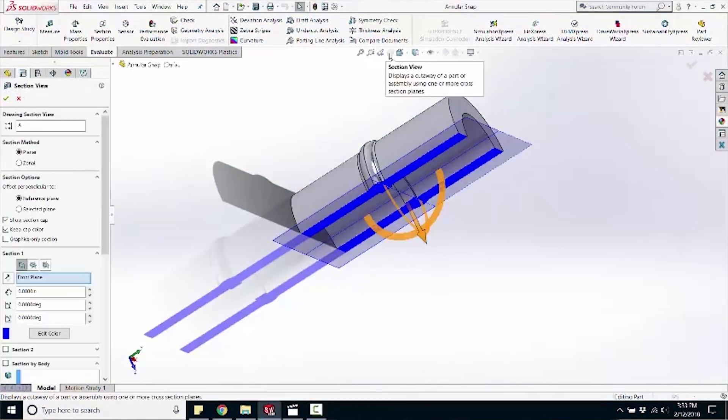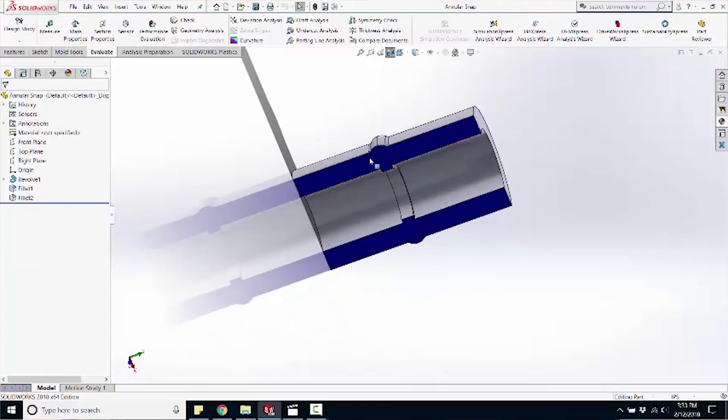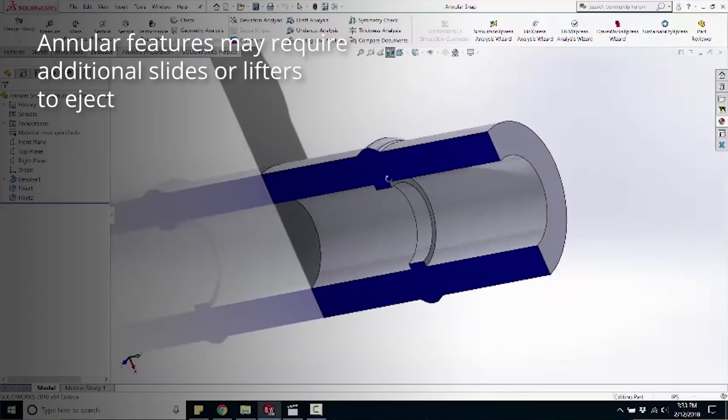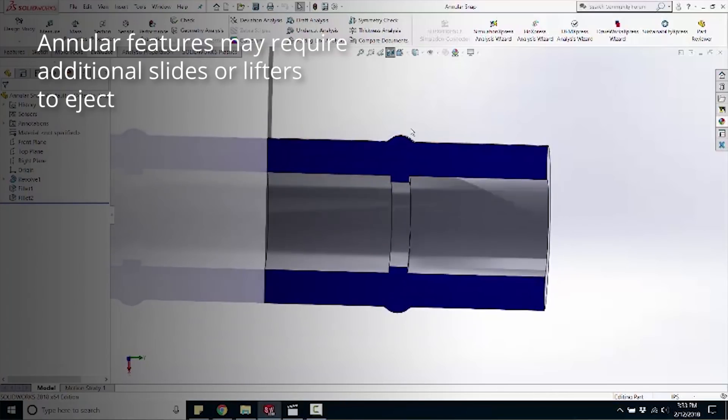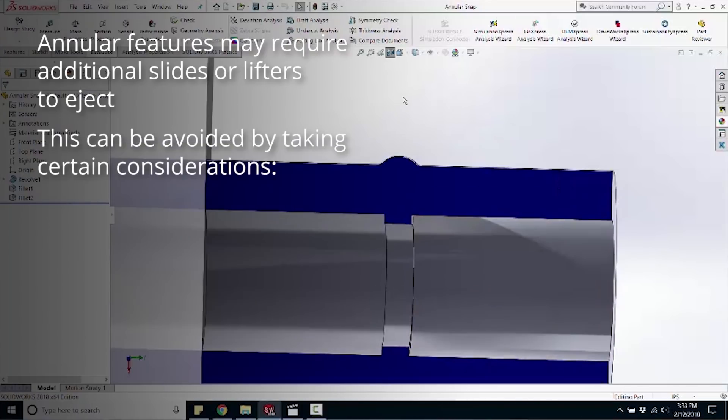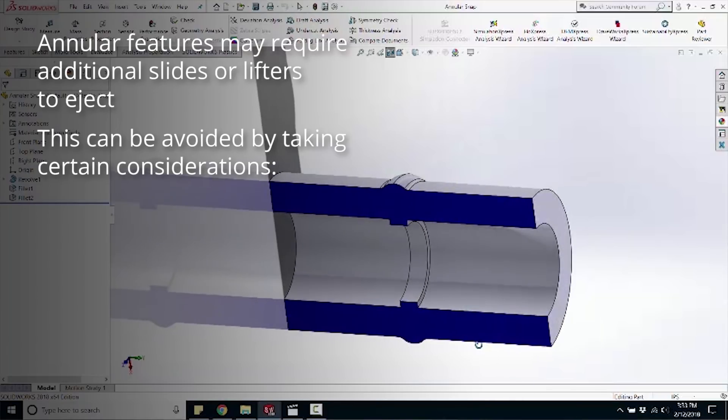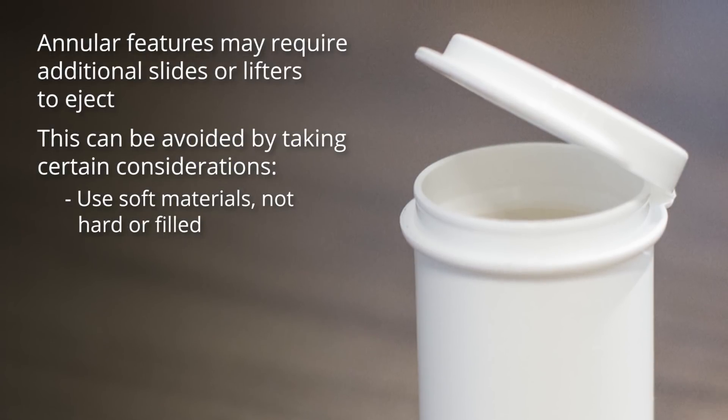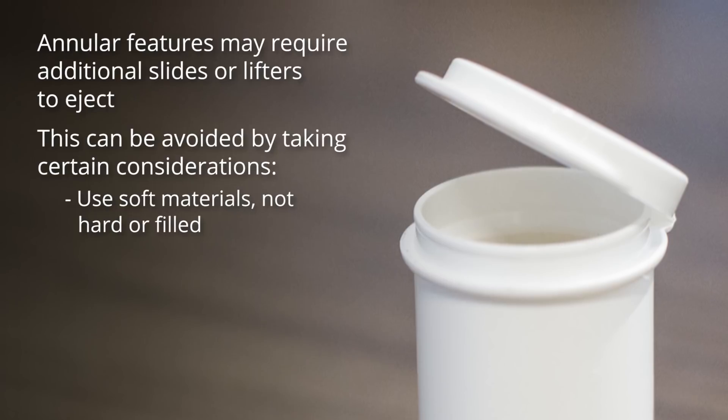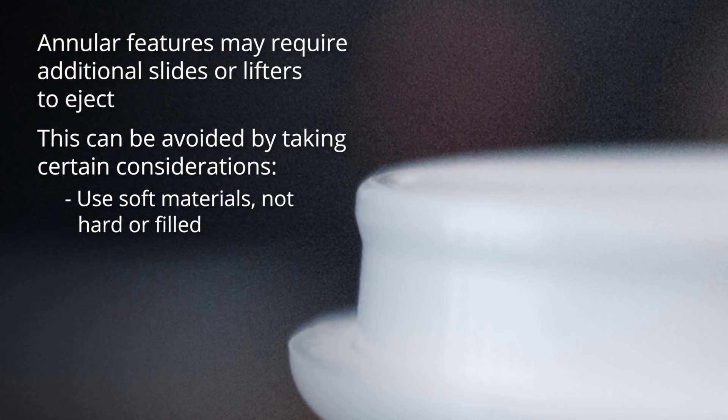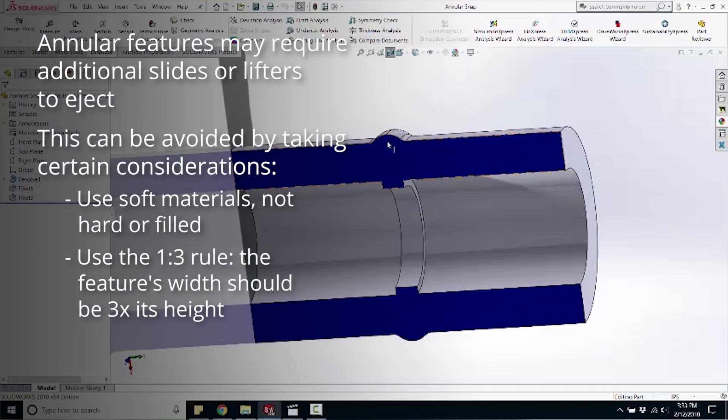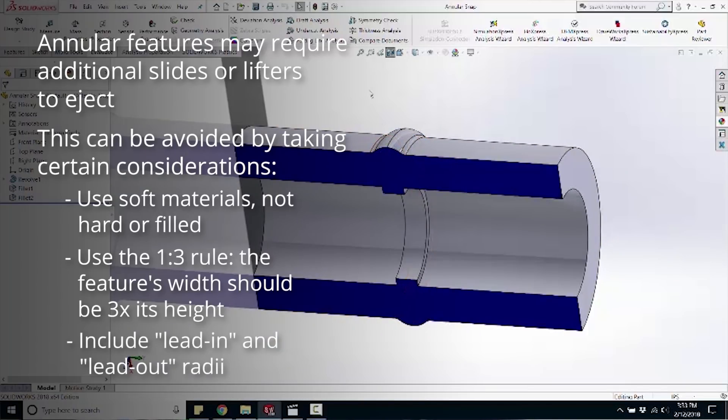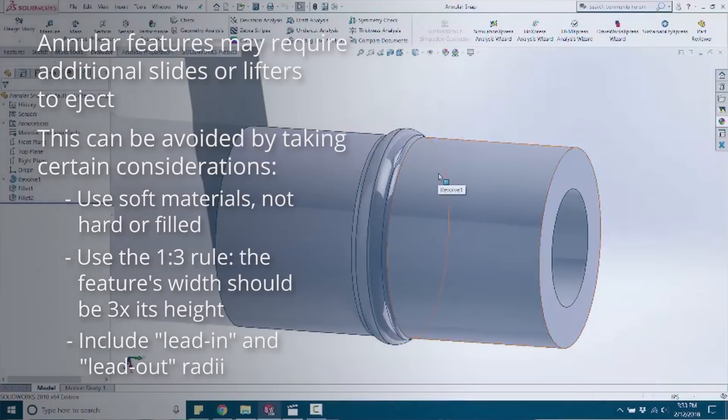If I were to cross-section this part, a lot of times I see stuff like this. If you had this feature on the outside of the tool, you would need some type of slide or some lifter to get this geometry out of the way. With this particular annular snap, if you needed this to pop out of the slide or pop out of the cavity or core, there is a way to do this. One, it depends on what type of material you're using. You can't do this with glass filled material or hard materials like polycarbonate. It'll shear this area off. But if you have something softer like nylon, maybe even PBT, polypropylenes, high density polyethylene, you can actually get this feature to snap out of the cavity or core block. So I use the one to three rule. The width is three times as large as the height. Also you have a lead in and lead out radius. If you have anything sharp here, as this goes to eject and pop off, it'll shear this completely out.